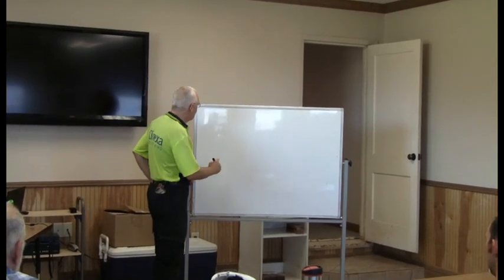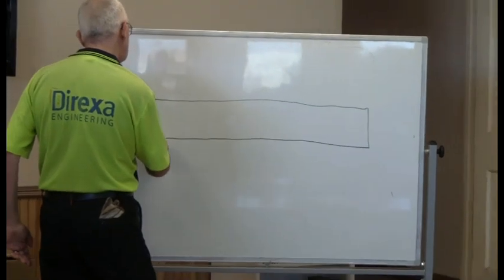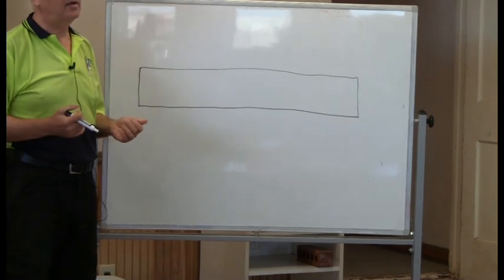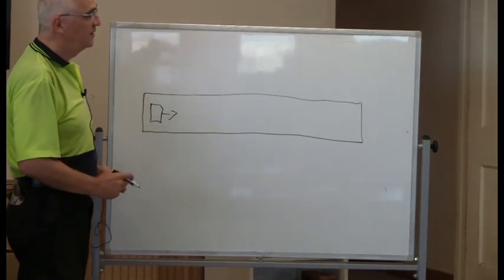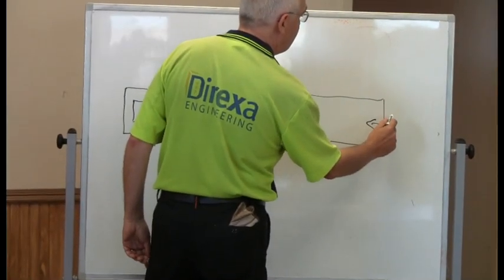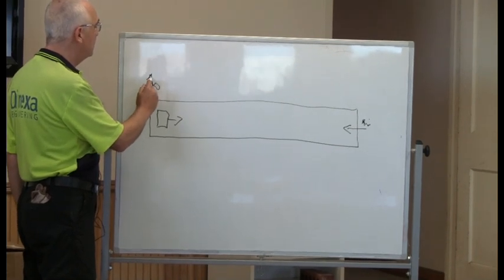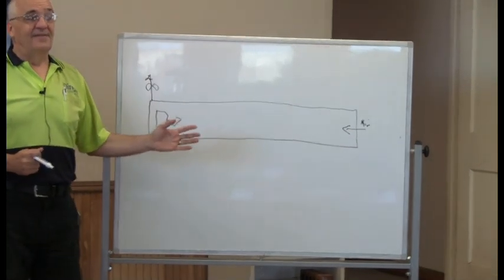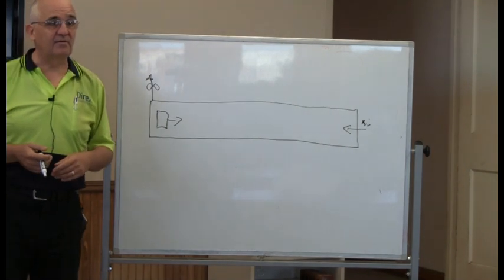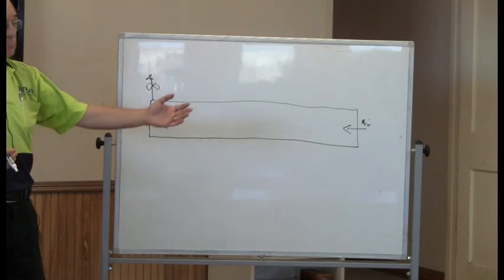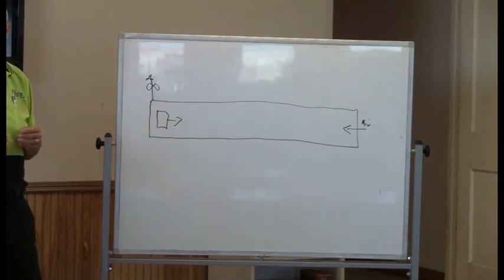Bear with me. So technically, a tunnel kiln is a tube which works in a simplified way as a heat exchanger. So we have product, a mass of product moving into the kiln, and we have a mass of air entering the other way and escaping through the exhaust. That is a very simplified kiln. What goes in goes out. In a sense, that's the old 50 years old kiln with no doors and exhaust. We rely on the exhaust to pull the air into the kiln, and that's a relatively simple process.